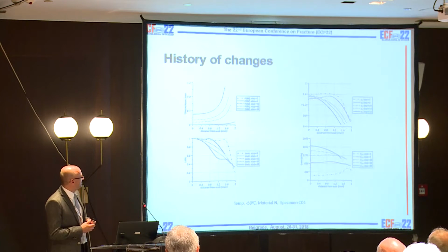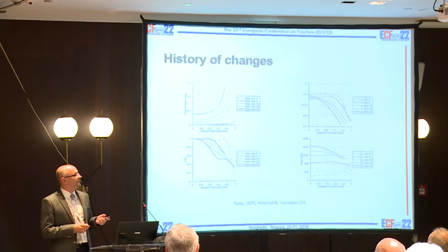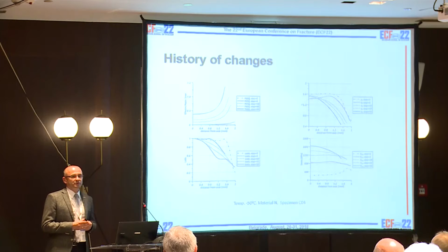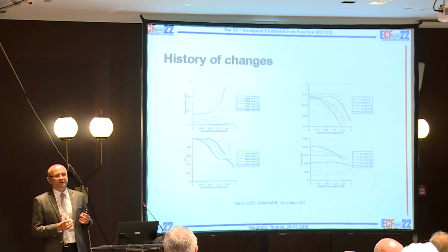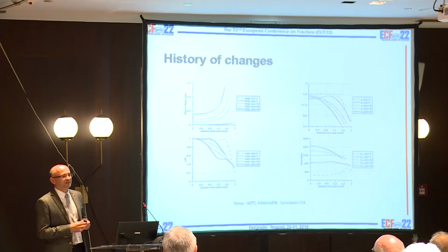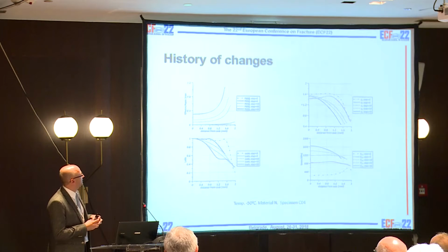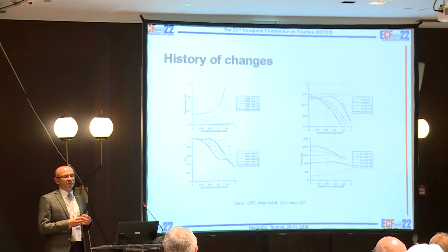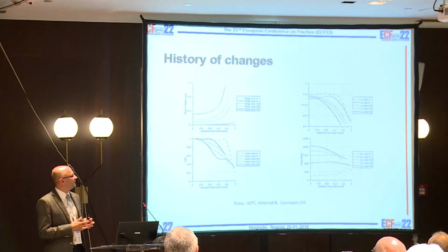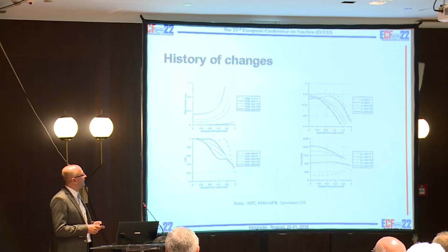So, the second specimen, CO4. As you can see, again, plastic strain increased gradually, and they are from the very beginning, at least at the central part of this specimen, accompanied by high triaxiality. It's a good environment to develop voids. They easily grow. So we thought that we can find cleavage in the area dominated by ductile just because these voids grow gradually, and when we met conditions for developing cleavage, there is no place for cleavage. The whole critical area is full of voids or other things connected with ductile mechanism.